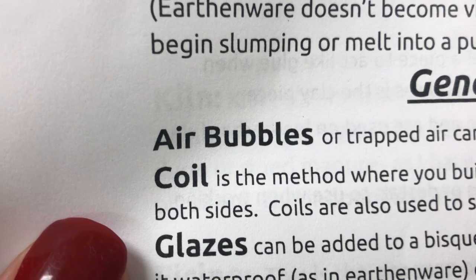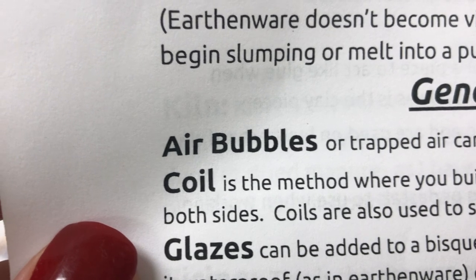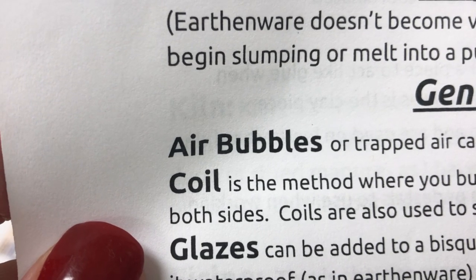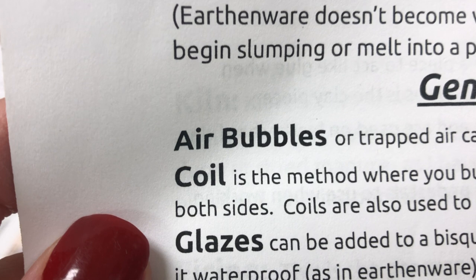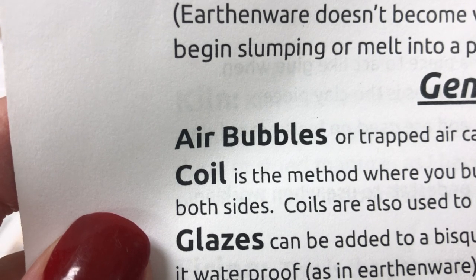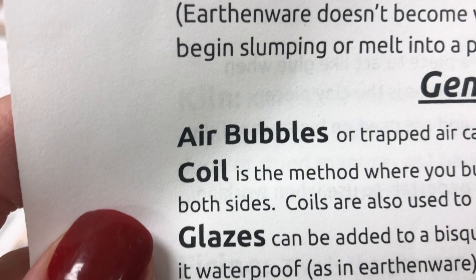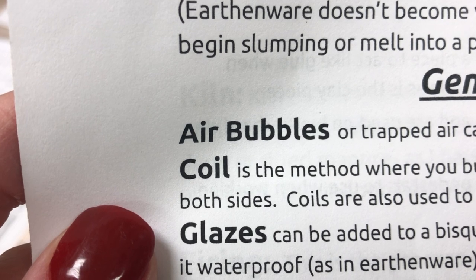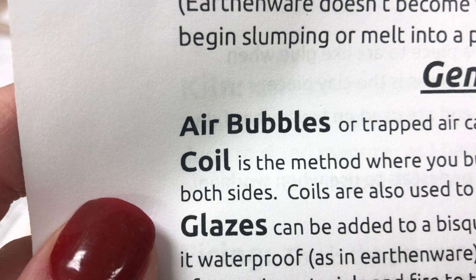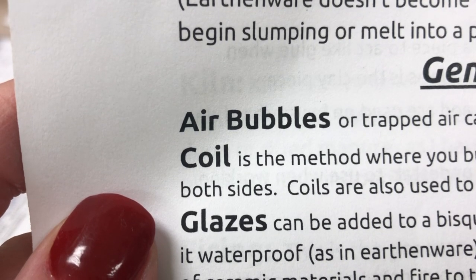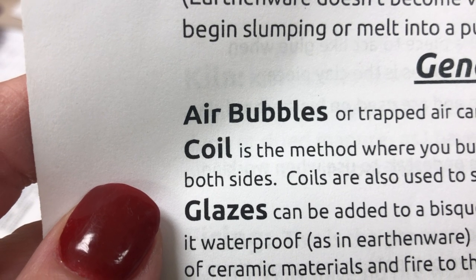Now on to general vocabulary words. Air bubbles or trapped air can cause difficulties. If you're throwing on the wheel, air bubbles will throw your piece off center. More importantly, if you have trapped air in a piece being fired, it must be fired extremely slowly so the water vapor can escape. I always have students vent a trapped air pocket with a single vent hole using a needle tool, so it doesn't blow up in the kiln — because water vapor will make it blow up.